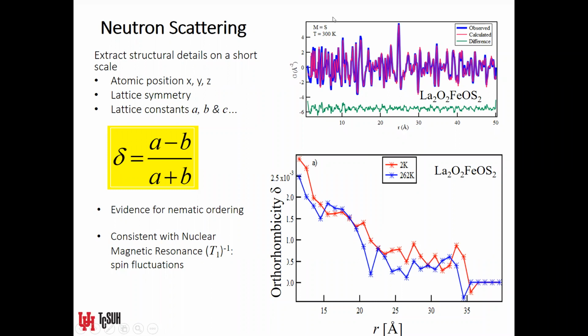At the top, we have the pair distribution function. From this top figure, you're able to extract A and B parameters. Those A and B parameters go into the makeup of this orthorhombicity plot, which we're showing. The orthorhombicity is plotted as a function of r. You can see that at small r's, at small distances, or shorter and shorter scales, the orthorhombicity takes on larger values. If you look over larger and larger scales, the orthorhombicity decreases. So the PDF technique gives you some indication that on a short scale, there is orthorhombicity, or a breaking of the tetragonal symmetry. And so essentially you have some nematic ordering occurring on the short scale.